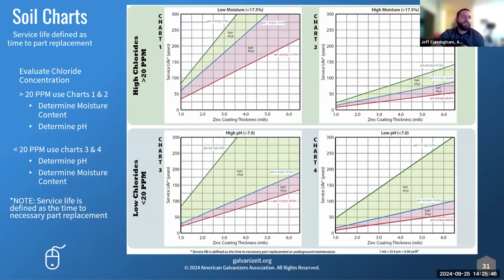And if you determine if you're working in high or low chlorides, or a high or low pH, or high or low moisture, then you can figure out which chart you're on. But just for demonstration, we'll say we're working in low chlorides and a high pH. We're going to be on chart 3. And then, of course, about 4 mils is a good estimate of zinc coating.